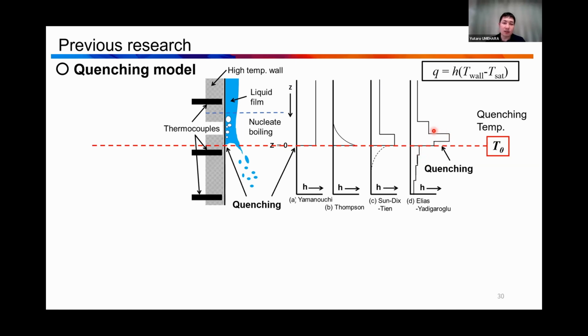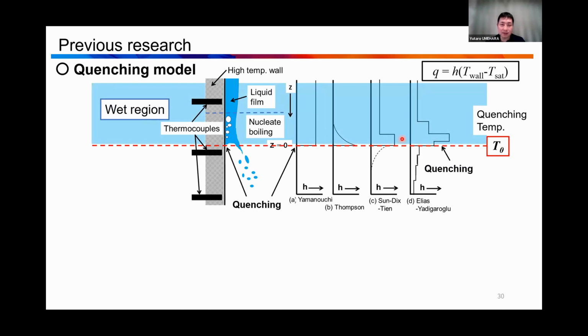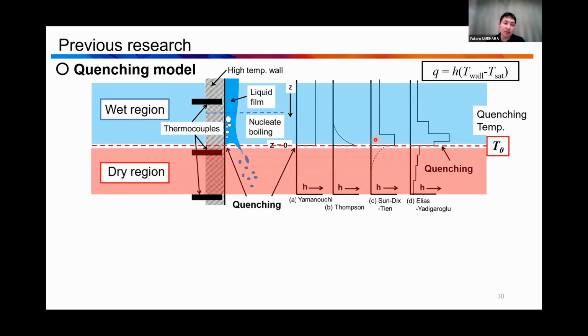And they called this region the wet region, and this region the dry region. Their quenching model is composed of three components: the wet region, the dry region, and the quenching temperature. And finally, they added some heat transfer coefficient, HTC, distribution. So finally, we can get a kind of quenching model. We can solve the heat conduction equation by using this quenching model as a boundary condition.